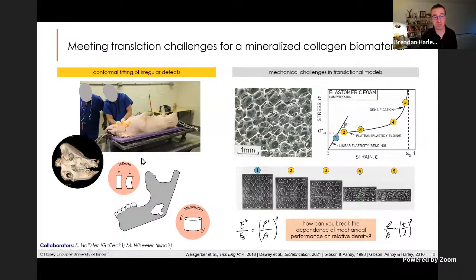We noticed two problems as we started to work on our materials to get into these larger defects. One of which is just the strength of the material itself. The thing that makes these scaffolds so exceptional for cell growth is that they're really porous. Cells can get into them, nutrients can get into them, oxygen can get into them, but also that means that all their pores make them relatively soft, which I'll get back to in a second. The other thing that was a real challenge is micromotion. You get an implant, you try to put it into a defect. You don't always have the luxury of being able to pre-design an implant to perfectly fit a defect. And so if you have a defect that is at all bigger than the implant you put in, your implant's going to move around a little bit.